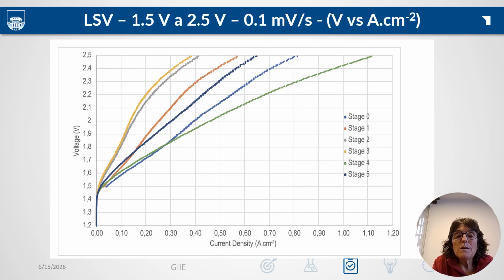This figure shows the polarization curves during all these stages. The behavior up to the regeneration step was similar to the first assembly. Curves shift toward higher potential, but the post-regeneration behavior is very different. After stage 4, the polarization curve actually slightly exceeds the original baseline. We attribute this to the acid acting as a post-synthetic activation step on a partially activated commercial membrane electrode assembly.